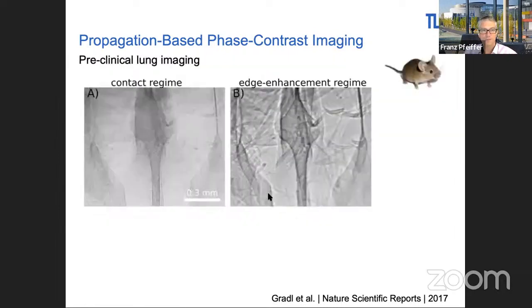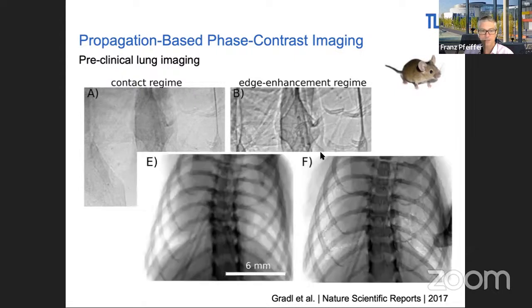We have employed that a lot for doing small animal research, in particular preclinical lung imaging. This is very close in the nasal airways, where you see nice contrast enhancement due to the edge enhancement. And this is now the full animal, the lung, and you see, of course, that you can nicely see more lung structure compared to a simple blurry attenuation image. We've been doing that because we have a large focus on lung imaging here in Munich, and quite a couple of research groups interested in that. That particular experiment was also done in collaboration, for example, with a group at Monash University that is also quite keen on this subject.